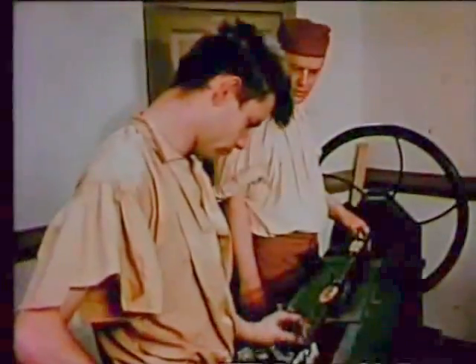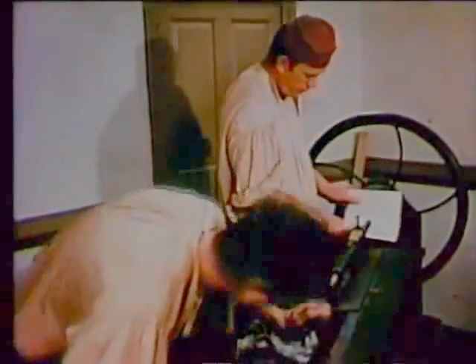When you're taking a heavy cut, you have to clean off the bits every inch or so. The borings are saved and used for flux. Occasionally, the barrel is cleaned and checked for straightness. Bends and crooks can be seen by sighting through it at the window. These can be hammered out on the anvil.